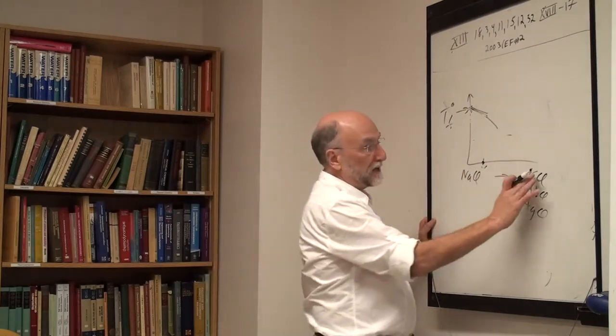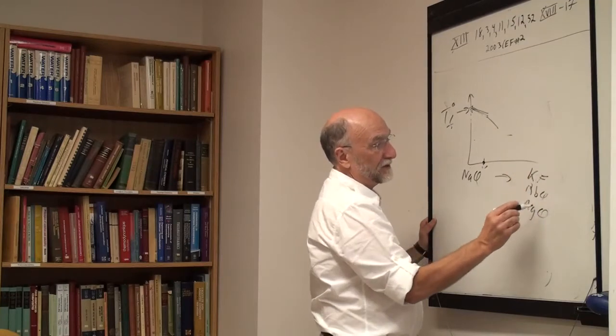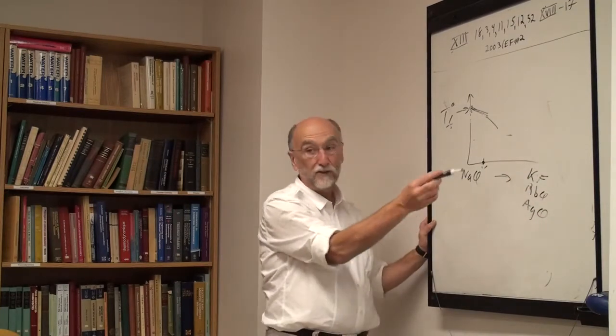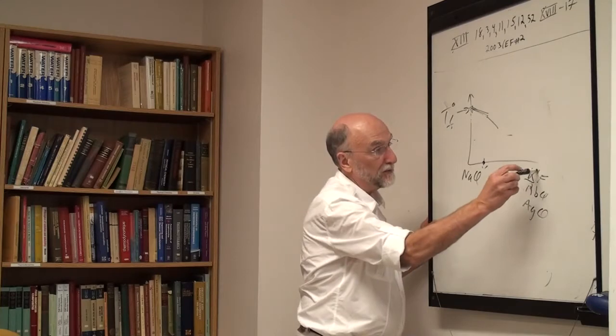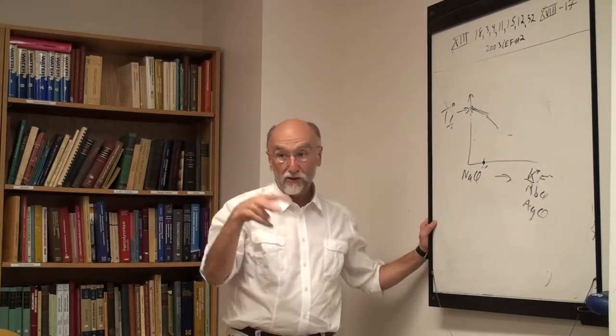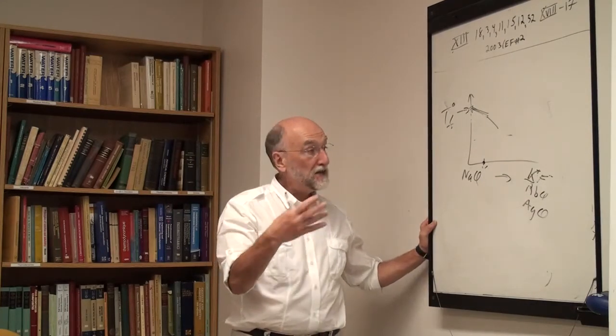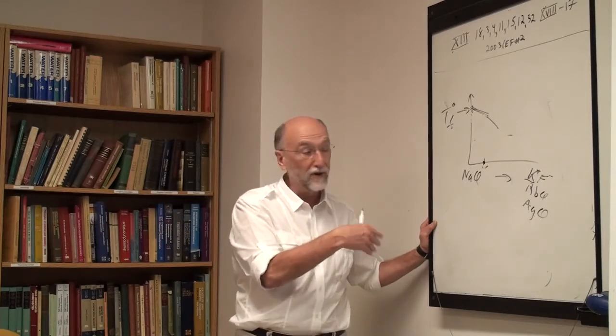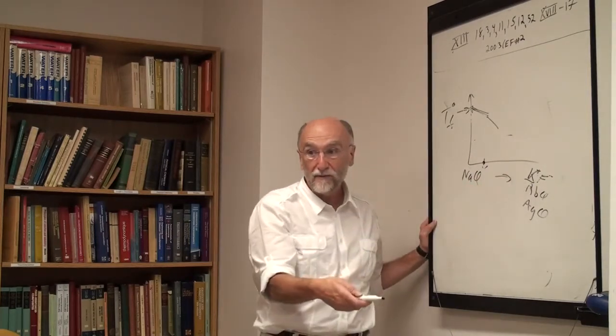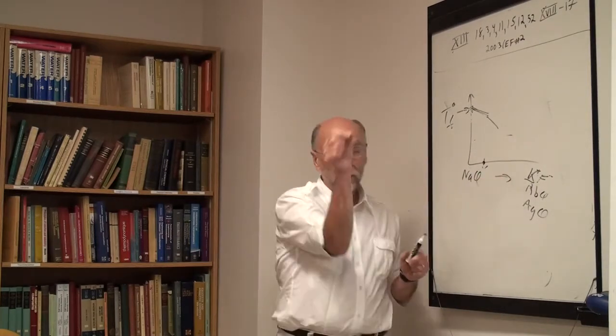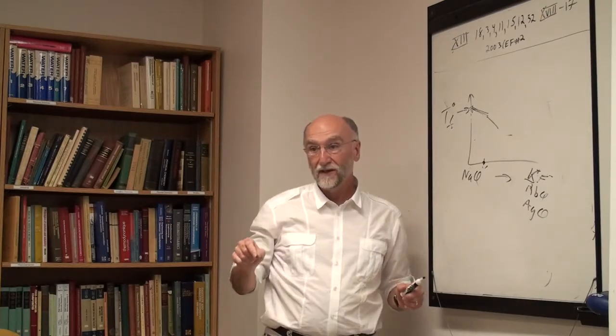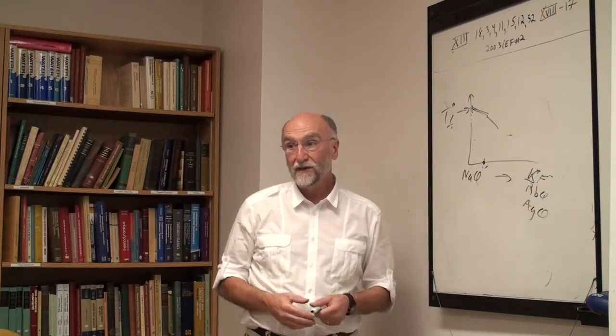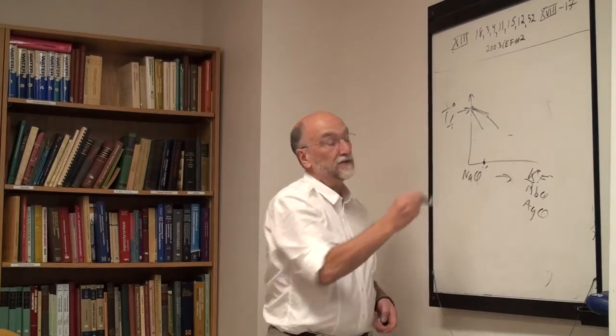Okay, but let's say I added potassium fluoride instead of potassium chloride. Now the potassium and the fluorine ions basically go in as 2 independent particles. The ideal mixing term is not what it was before with potassium chloride, now it's 2 times. The potassium ion and the fluorine ion each mix independently, so they give you twice as much entropy. So I'm going to get exactly twice the limiting slope.